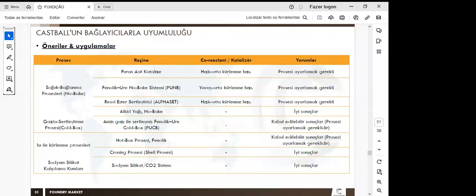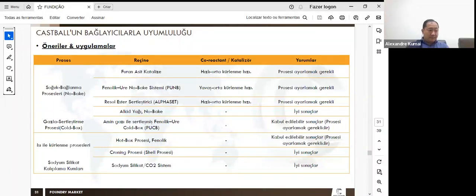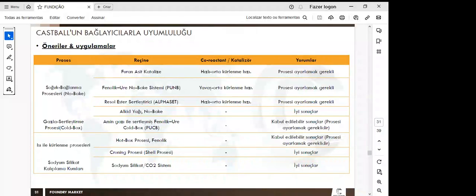Well, now we talk a little bit about compatibility with the binders. Okay. Castball was tested with many foundries, and we are learning more and more. We put here some suggestions that we have seen with our customers. For example, for furan resin, no-bake process, Castball is more suitable when we use a fast to medium cure rate. Okay. With phenolic urethane, no-bake too, we suggest a low to medium cure rate. It's better when we use this type of resin and catalyst. The behavior is better, okay? The results are better when we use these types of resins.